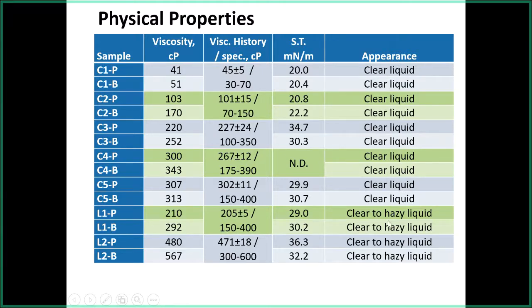You can see the appearance is the same in all of these. At the C1 pairing, there's a little bit higher viscosity for the bio-based material, but it is almost within 1 standard deviation and well within specification. The surface tensions are really very close. The point I'm going to make here over and over again, and we see this with these bio-based materials, is there's a little bit of bias with the samples we have. They tend to be more viscous. They tend to give you higher surface tension. And what we think is going on is the distribution of the polyether is slightly different. There's a little more EO, a little higher average molecular weight. So these two suppliers are using slightly different processes perhaps, but they're well within tolerance.